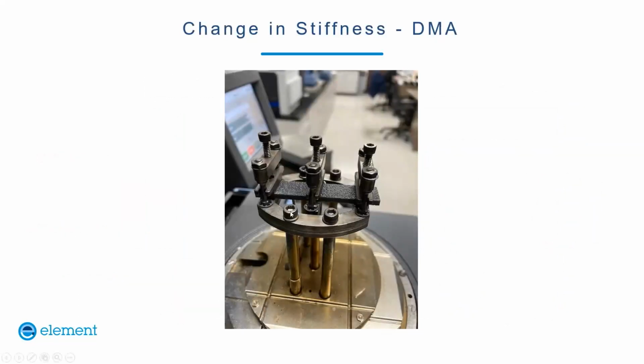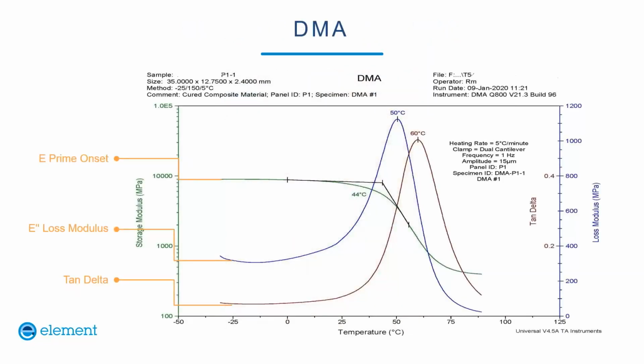Going too fast there. The clamp oscillates in a sinusoidal way, and we measure temperature as well, and we measure force and deflection as the clamp oscillates. A furnace fits around the outside of this and then slowly heats up over a pre-programmed range. We measure the change in the forces and deflections with temperature, and we get a curve like this. The results are reported as three different curves.